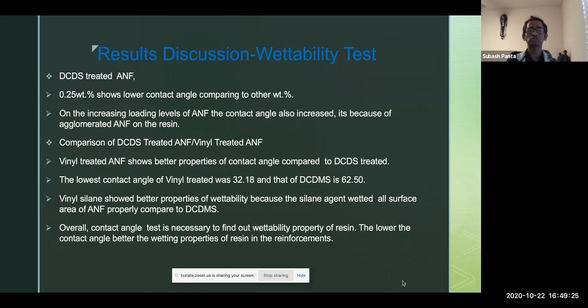So vinyl silane showed better wettability because the silane agent wetted all surface of ANF properly compared to dichlorodimethyl silane treated. Overall, contact angle test is necessary to find out wetting property of resin. The lower the contact angle, the better the wetting property of resin in the reinforcement.